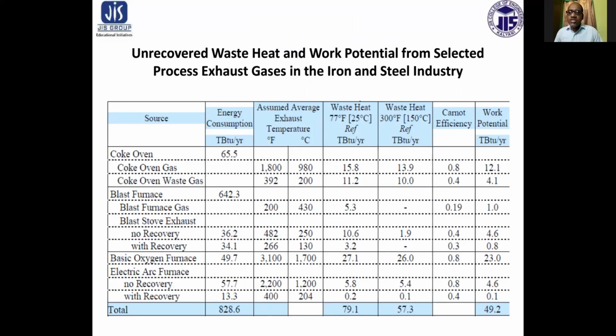Now, this chart shows unrecovered waste heat and work potential from selected process exhaust gases in the iron and steel industry. In a coke oven, the annual energy consumption is 65.5 trillion BTU, and that includes coke oven gas and coke oven waste gas. The temperature for coke oven gas is 1800 degrees Fahrenheit, that is 980 degrees centigrade, and for coke oven waste gas 392 degrees Fahrenheit. Waste heat is 15.8 trillion BTU per year for coke oven gas and 11.2 for coke oven waste gas.